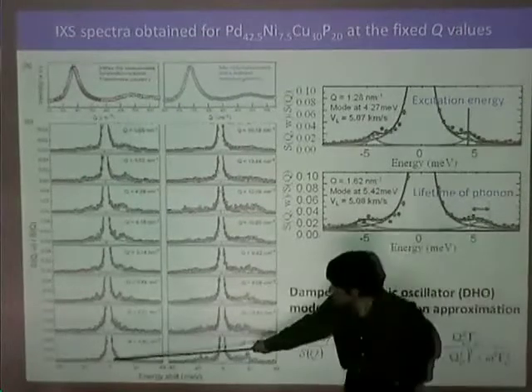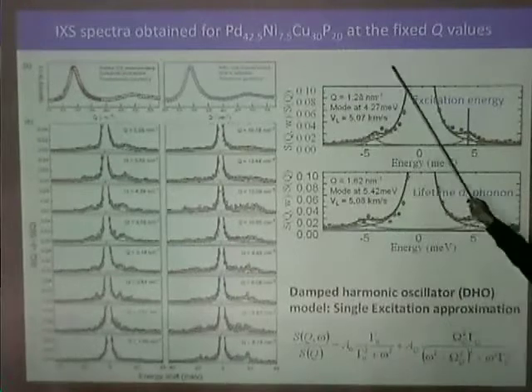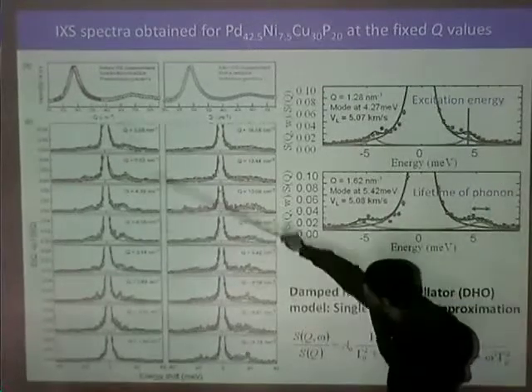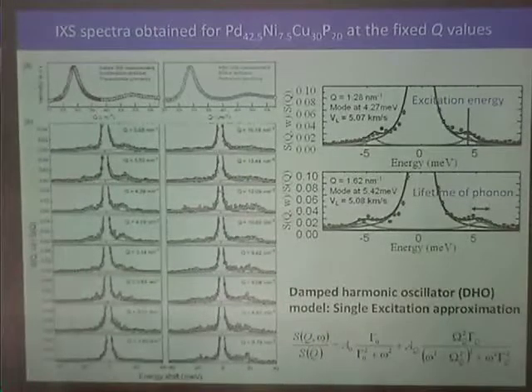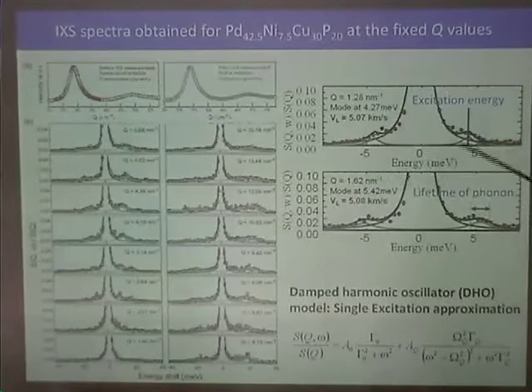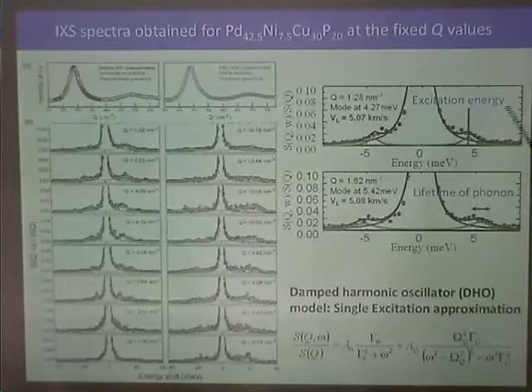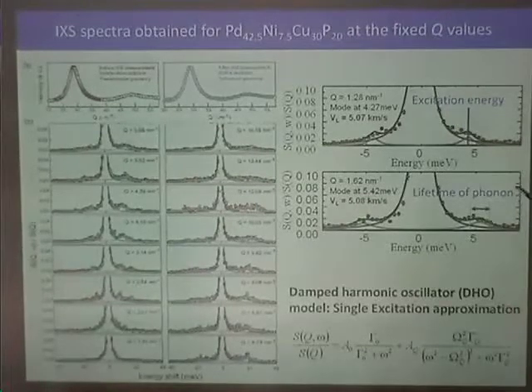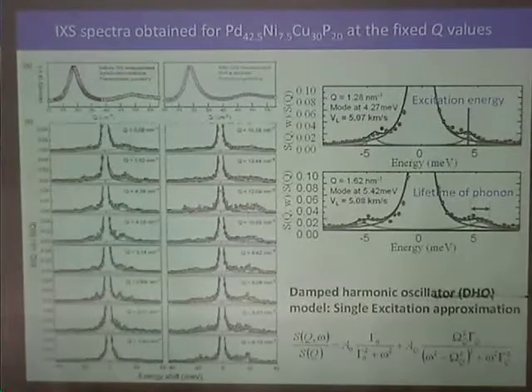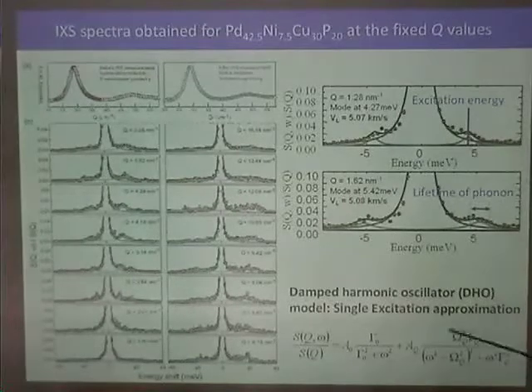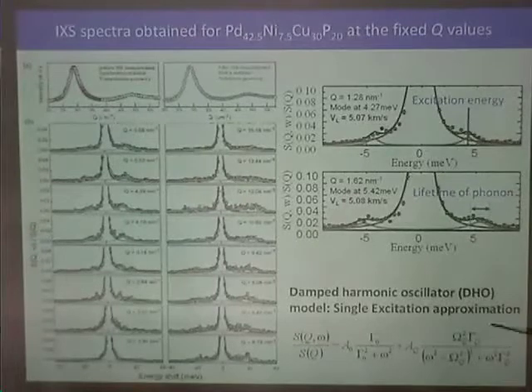This is the IXS spectra obtained for this metallic glass, palladium, nickel, copper, phosphorus. This is a low Q and high Q region, and these spectra are obtained for the very low Q region. This peak means the excitation energy of the phonon, and this bandwidth means the phonon's lifetime. By fitting the DHO, damped harmonic oscillator function, to this observed data, we have obtained the excitation energy, and gamma is the lifetime of the phonon.